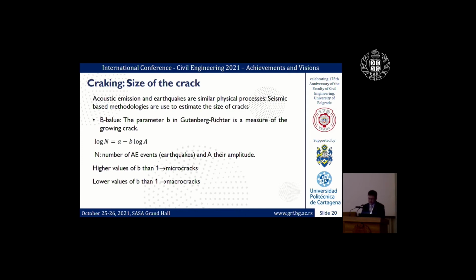But the methods in seismology can be translated to acoustic emission and can be used to monitor the size of the fractures. Here we have an example of that one. It is the b-value method, which is based on the fact that the number of events with a given amplitude has an exponential decay. So if we take logarithms of the number of events and the amplitude, we get a linear relationship. The slope of that relationship is the parameter b, which is used to characterize the cracks. It is used in seismology to characterize big fractures, and it is used here to characterize the small ones.